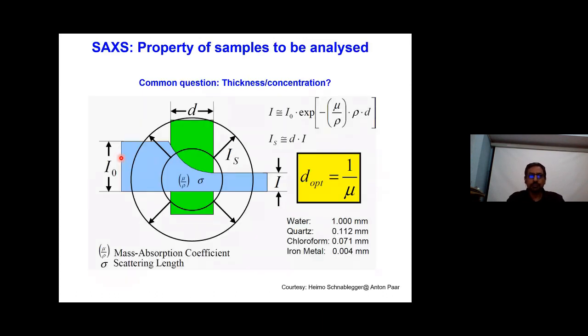Some of the questions which come into the picture are what type of sample to be used, what should be the thickness, or what should be the concentration. The thickness or concentration of the sample depends upon its mass absorption coefficient. Some of the mass absorption coefficients I have mentioned over here. Simply, the higher the atomic number of the material, the higher the absorption will be. So you can see iron has a very small optimum thickness which can be used for scattering the X-rays.